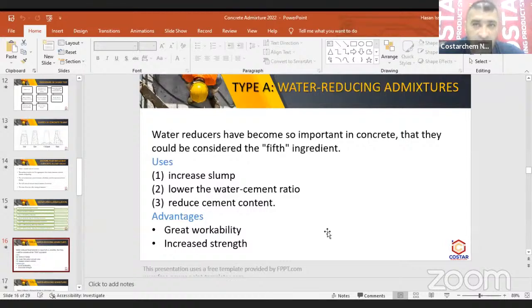And this again will interfere with the water cement ratio, as water will be divided by the amount of cement. So actually, you should subtract your amount of admixture from your total water. If your water is 160 and your admixture is 5, you have to add 155 plus 5. All right, that's very important, so that your water cement ratio will not change. And trust me, it really affects it a lot.